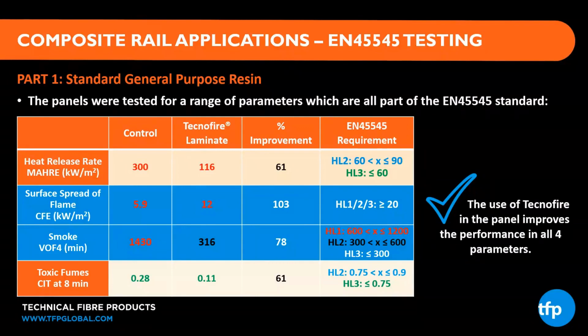If we look at surface spread of flame here, a higher number is a higher level of performance. The control comes in at 5.9. The Tecnofire enabled panel offers 100% improvement up to 12. So we've significantly reduced the ability of that part to burn in a fire event. If you look at the requirements to EN 45545, they're very, very stringent. So all three hazard levels define a surface spread of flame requirement of greater than 20. So we're not there yet. We've got significant improvements from 6, but again, we're confident a small inclusion of a secondary fire retardant additive would push us forward.